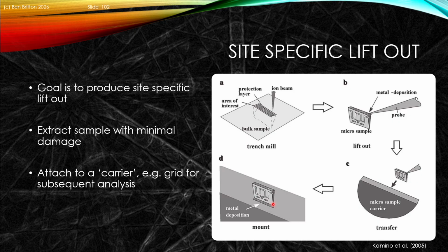And effectively, once it's been transferred onto the carrier sample, we can then perhaps thin the sample or perform subsequent analysis. So the goal is to produce a site-specific lift-out. We want to extract the sample with minimum damage, especially at the last thinning layers. And we're going to attach this to a carrier that can be manipulated. For instance, it can sit on a different part in the microscope, or we can use this to transfer from one instrument to another, to move this, for instance, into a TEM.